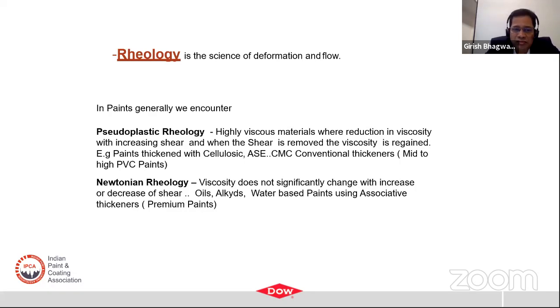So there are two types of rheologies that we encounter in paint. One is the pseudoplastic rheology, which is important for high PVC, mid PVC paints, where we end up adding a lot of water for dilution. These types of materials show a reduction in viscosity as we increase the shear. So what does shear mean? We stir the paint; during paint manufacturing it is dispersed using high-speed stirrers, and during application we mix the paint, maybe pick it up on the brush. We'll talk about the rheology profile in a couple of minutes, but in pseudoplastic rheology there is a reduction in viscosity as we apply the shear, and it is gained back slowly as we remove the shear. Now that helps, especially in high PVC paints. It's good because of the significant dilution that happens.